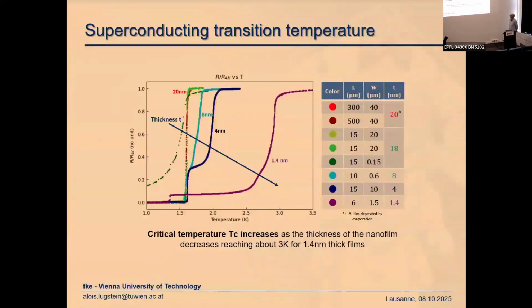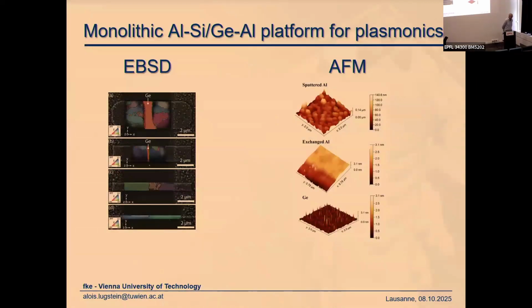Another nice feature which we also don't understand up to now is that when we cool these thin sheets down, we saw an increase of the transition temperature. So the thicker layers, with about 20 nanometers, become superconducting at about 1.5, 1.6 Kelvin. If we get thinner and thinner, and this is the thinnest one that we achieved up to now, this transition happens at about 2.8 Kelvin. So, as I mentioned, these aluminum sheets or aluminum wires are single crystalline when they are narrow. So the wider sheets are polycrystalline, but as soon as you get below 500 nanometer widths, you see these are single crystalline aluminum sheets, and they are really smooth. So the surface is extremely flat.